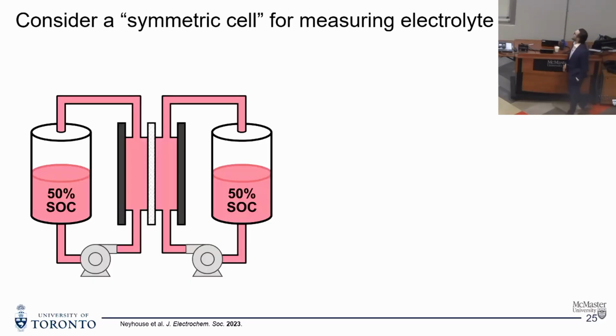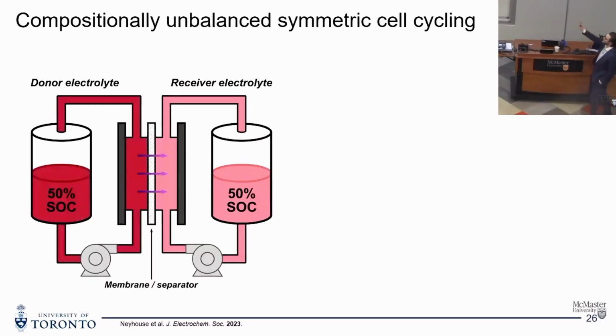So why this would be a starting point: a colleague asked if we could use this, and I modeled it, and it showed that it's really good for ignoring the effects of crossover. But we looked at it and said, well, what if we just increase the concentration of one side? So we're still able to rock back and forth from this 50% state of charge. But if we have a higher concentration of this side, we are going to induce some diffusive crossover. And we can still cycle the membrane, or still cycle the cell.